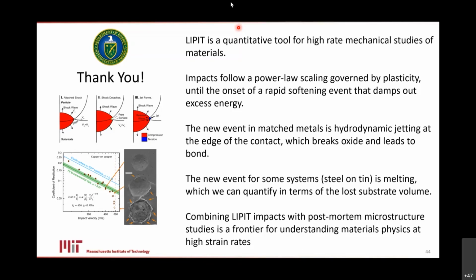don't take this to the bank. But here's how I view it in my head. The particle strikes, and you get incredibly rapid deformation at the interface. The metal starts to liquefy in regions, but it probably does so in bands, right? Where dislocations are slipping together, you probably get little pockets or bands that are melting first. And once you have liquid in there, that has zero tensile strength, right? So you've got a whole bunch of zero strength material, and it may be woven all around other solid portions of the material. And so now the zero strength stuff is unstitching the solid, and it's letting other portions somehow rip free. They don't have to melt; they just go along for the ride somehow. That's my mental model of what's happening, but we don't know. We can't see it. There's probably some sort of liquid-like layer in there that's letting things smear around.